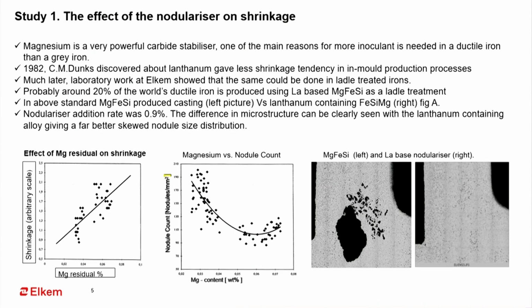So in this case study, using lanthanum bearing ferrosilicon magnesium helps to control the microporosity. In the case of shrinkage factor, residual magnesium also you have to consider, because when the residual magnesium is on the higher side, that also increases the shrinkage tendency. Normally foundry people think if residual magnesium is on the higher side, there will be no compacted graphite. This is correct. But another problem is that definitely there will be more chances of shrinkage tendency.